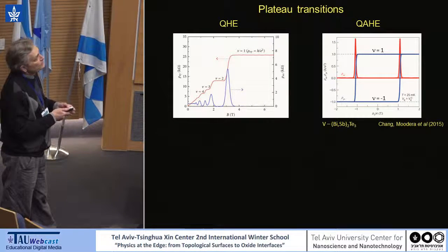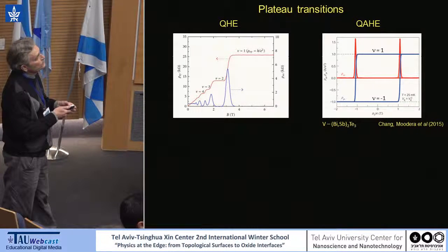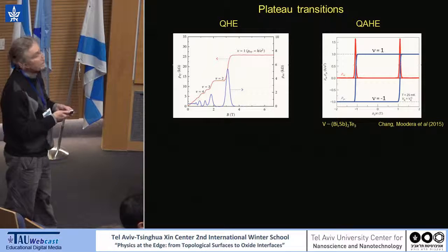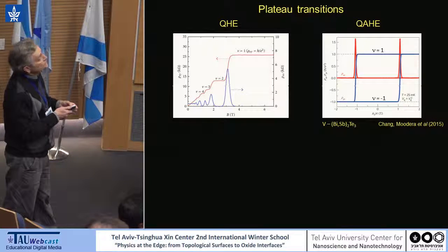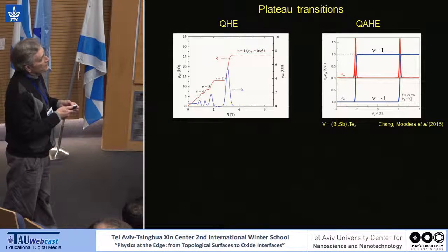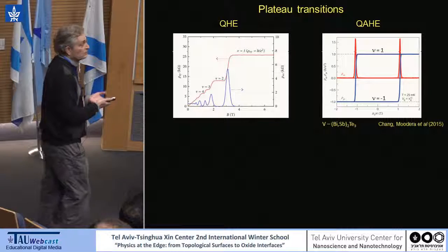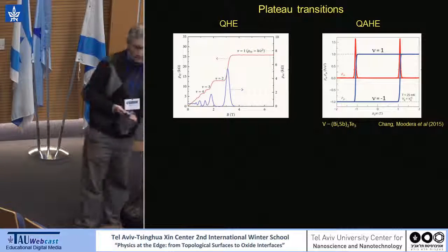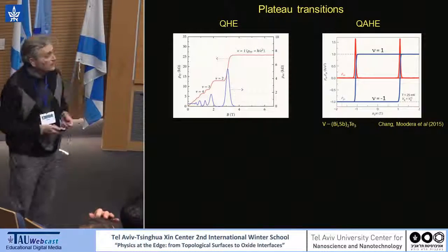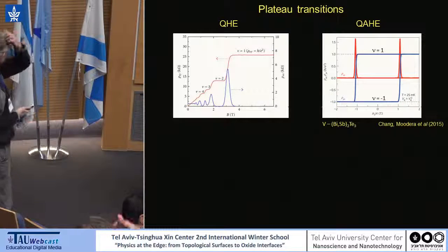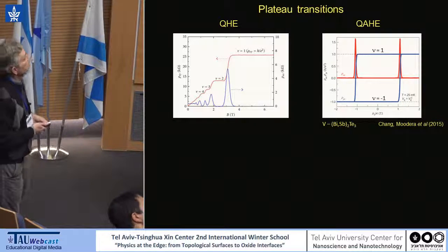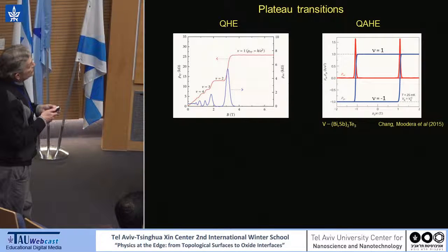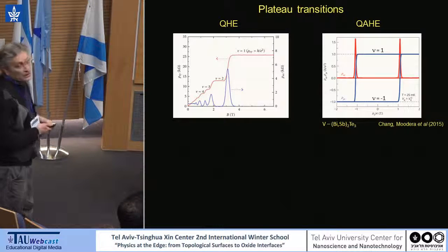So we can magnetize the ferromagnet entirely at high field, and then when we come back to zero field, it remains fully magnetized, and it actually remains magnetized even when you go to negative field, namely you are in a metastable state. The third important difference, which I'll mainly focus on, is the source of the physics of the plateau